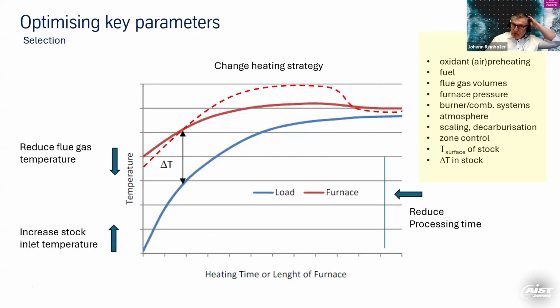So what to do? What are the variables and the parameters we can optimize? We can obviously try to increase the stock inlet temperature. That will help. If we come in with 300 degrees, obviously we need less energy to heat it up in comparison to room temperature. We can try to reduce the flue gas temperature, because as we have seen, the flue gas is the highest loss of the furnace. So if possible, we want a low flue gas temperature. How can we achieve that? It's not so easy. We have to improve the heat transfer in the furnace, or we can make the furnace longer, which we usually don't desire, because we want to minimize the footprint and also the cost of the furnace. So you have to make decisions in the end. There's no 100% one-fits-all solution.